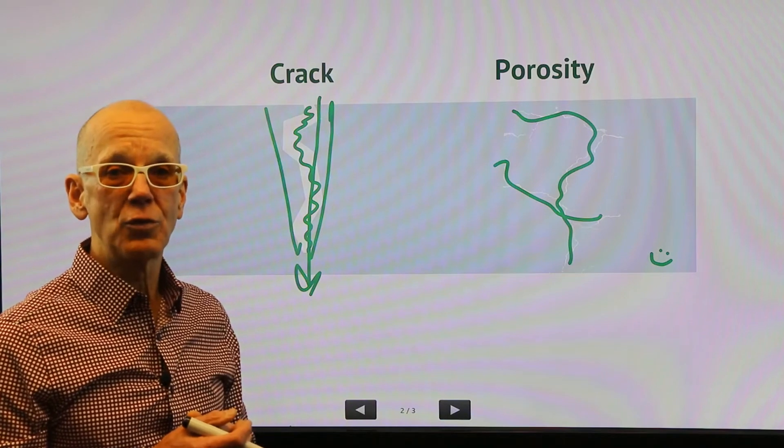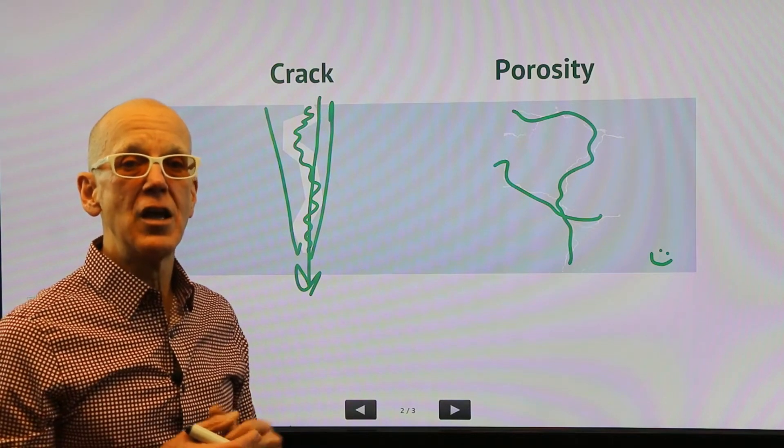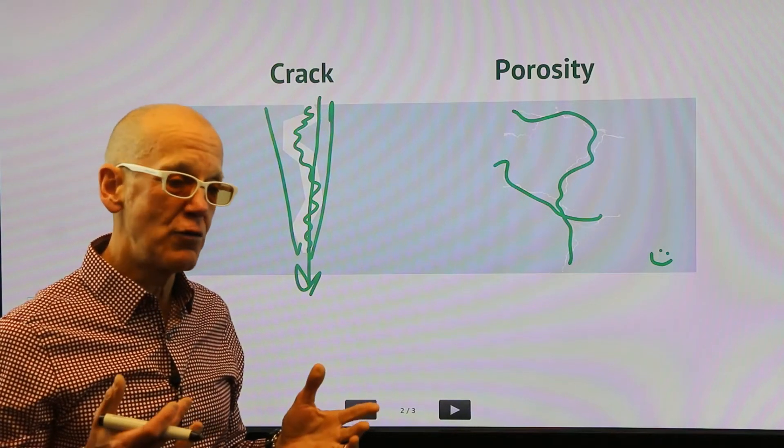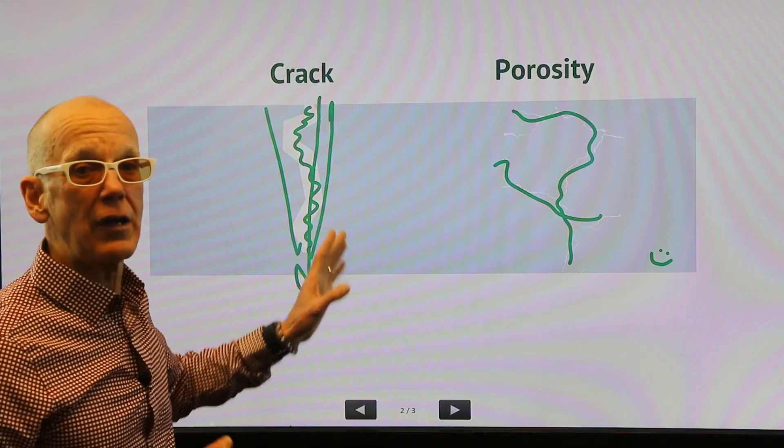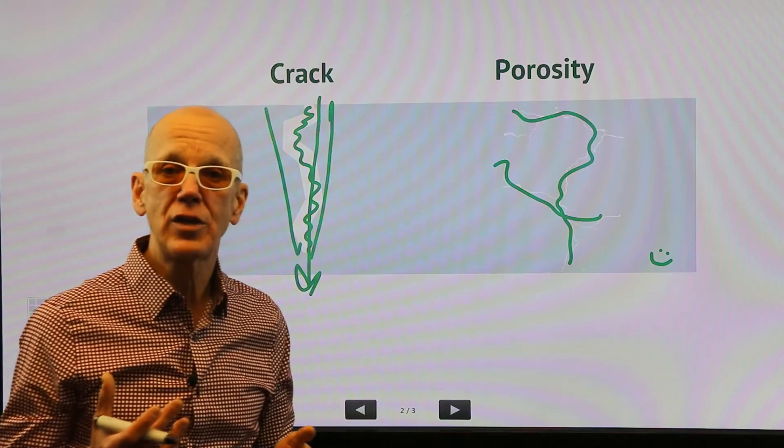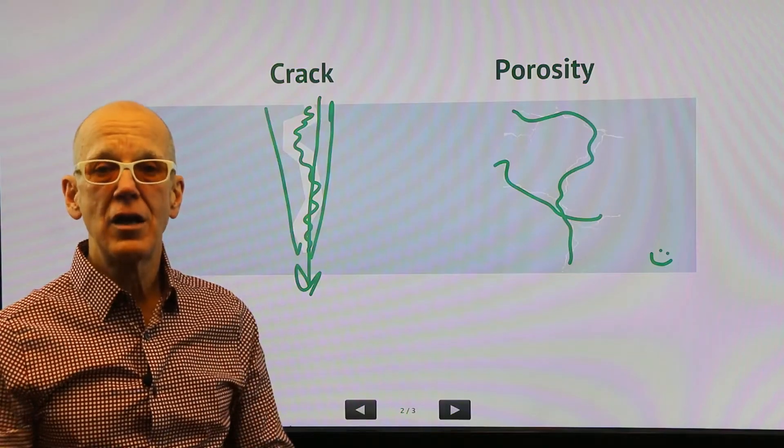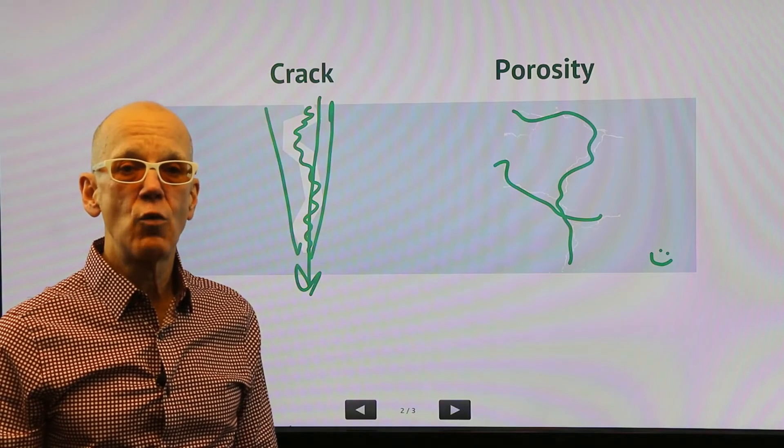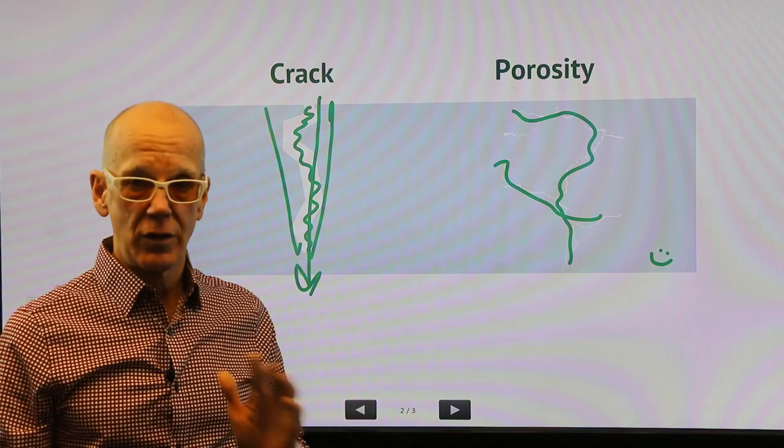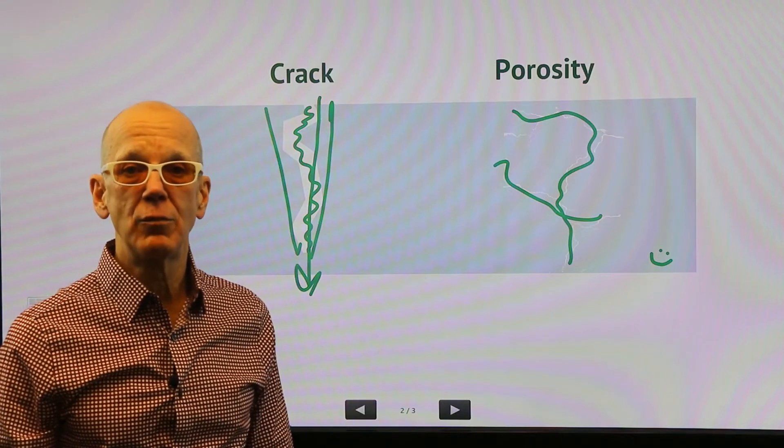Oftentimes folks will jump to the conclusion that impreg failed, but on further investigation you'll find that there's a crack. And some of the programs that we do leak testing and impreg on, if it leaks in an area that we know is prone to cracking, the casting will get scrapped and not even impregnated.